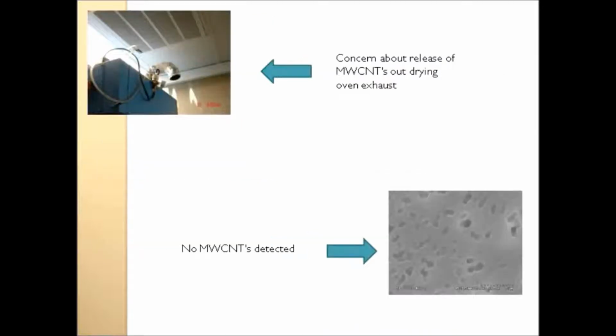They were concerned also about the possibility of, during a drying process, there would be a release of this material when they bake it and dry it. Once it comes out of that bucket, it's a slurry, and they put them in trays and they weigh them, or they put them in an oven and dry them. So they were concerned that there might be a release to the general lab atmosphere via the exhaust port. So we basically sampled there for an entire 8-hour drying cycle, and we found nothing, which was a good thing.